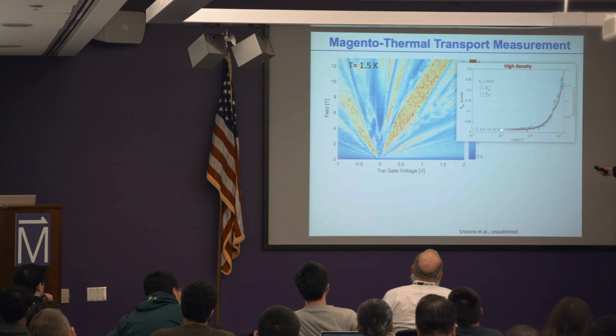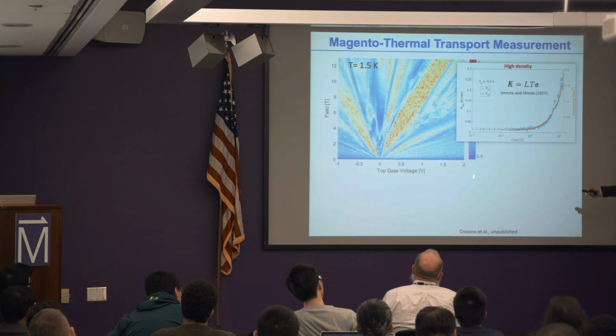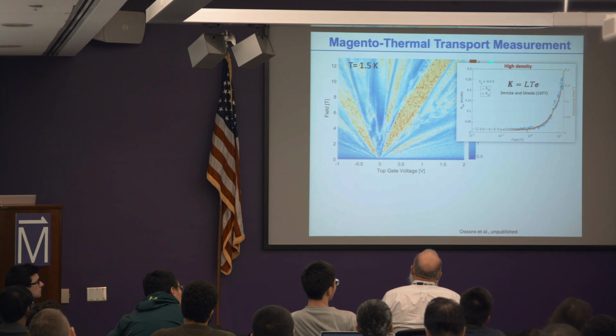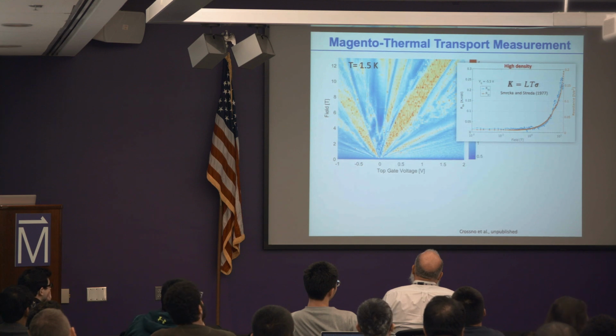If I cut at different densities, you will see that at high density, the thermal resistance actually goes up with the field. At the same time, the electrical resistance goes up with the field. And in fact, they show the same ratio, the same behavior. In other words, at high density, the Wiedemann-Franz law seems to work. In fact, it turns out it works component by component. It's not surprising in a sense. At high density, we can still describe it as a Fermi liquid modified by the magnetic field.